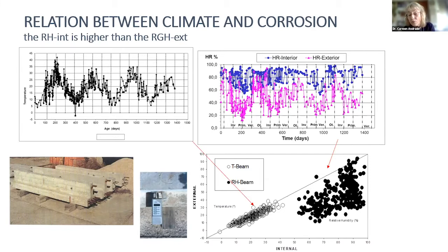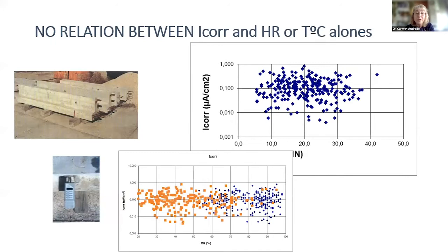This is not the first time that this was published, because the people from Sweden, Fagerlund and other researchers, were also studying that, and they realized by other means this sponge effect of the concrete. The concrete retains the humidity much longer than when drying. And when we plotted the corrosion rate versus the relative humidity inside, we didn't find any relation. There is not a direct relation. Also with the temperature, I think that this is temperature and this is the relative humidity inside. In that case, it is not the relative humidity that is controlling, as in some cases people think. No, it's not the relative humidity that controls the corrosion rate.